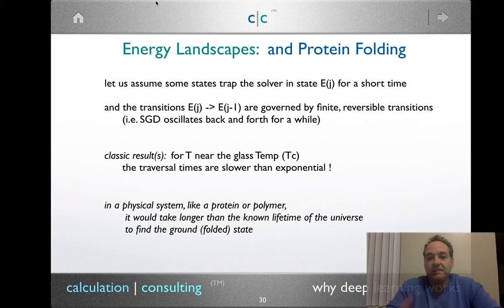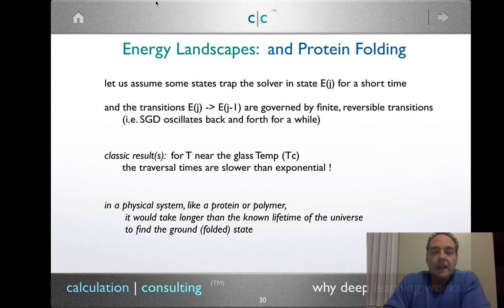In that situation, there's a classical result, which shows that for temperatures near the glass transition, the traversal times are slower than exponential. So what does that mean? By slower than exponential, think about how we solve when we do deep learning systems. When we run SGD, we have an annealing rate. So we're changing the step size. And usually the step size that we change, we use an exponential decay for our step size. So even something like RMSprop, go back to before that when we just do simple exponential decay on the learning rate in SGD, and that learning rate decays exponentially. So what I'm saying is that when you're near the glass transition, that learning rate would have to be slower than exponential. You would have to decay the thing really, really slowly.